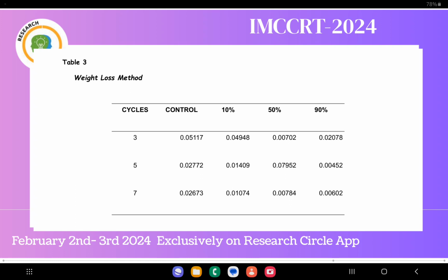Specific observations for cycle 3 indicate improvements with increasing concentrations, with the 50% concentration showing significant effectiveness. Similar trends are noted for cycle 5 and cycle 7. In conclusion, Mimosa pudica leaf extract demonstrates efficacy in inhibiting corrosion on dental instruments. The effectiveness is concentration dependent, with higher concentrations exhibiting better corrosion inhibition. Furthermore, longer exposure or more cycles enhances the corrosion inhibition effect.